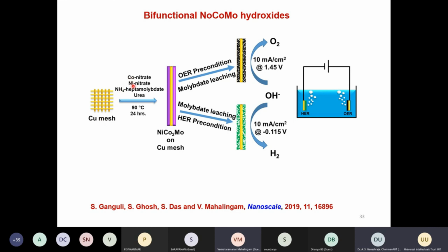But we have taken these three metals, and I'll tell you why. We wanted to understand each component, how nickel, molybdenum and cobalt improve the activity, particularly for the bifunctional activity. That means a catalyst which you use for both hydrogen evolution as well as oxygen evolution. So we coated this material on the copper mesh, and we did this precondition study as I mentioned before. What we interestingly observed is the molybdenum leaching that happens during this electrochemical precondition study. I'll explain why molybdenum leaching is important here.